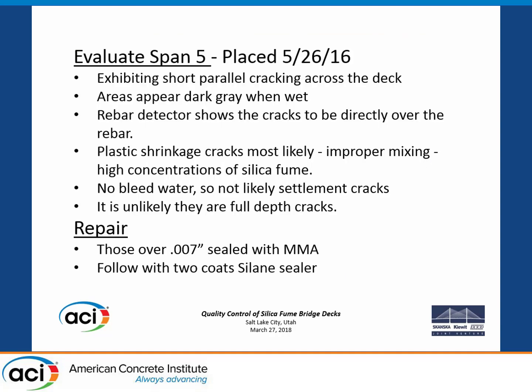So, my evaluation. Short parallel cracks across the deck. Up here when wet, dark gray. Detector shows the cracks over the rebar. Plastic shrinkage, most likely. Improper mixing. High concentrations of silica fume. You know, when silica fume first came out, everybody wanted to use the slurry. People didn't want to use the powder because they couldn't get it mixed in correctly. So I think that's what happened. There's no bleed water in this stuff, so it's not settlement cracks.